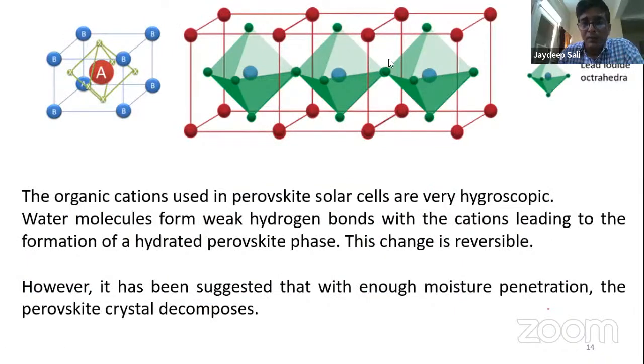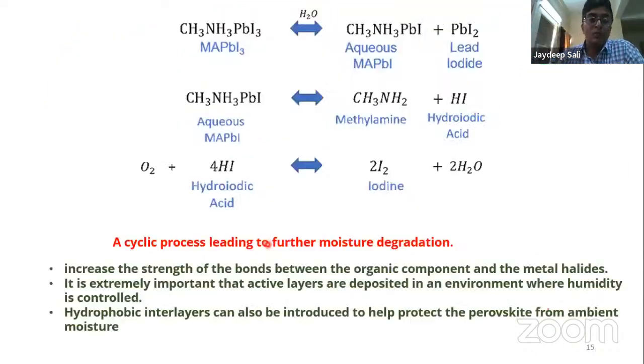One of the causes is that the organic cation that we have seen, A, that is used in the perovskite solar cell, is hygroscopic. So what happens? When water molecules penetrate the perovskite film, they form weak hydrogen bonds with the cations, and this leads to the formation of a hydrated perovskite phase. Of course, this change is reversible. However, when enough moisture has penetrated, the perovskite crystal decomposes.